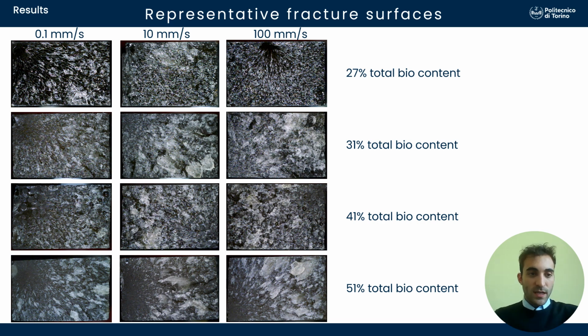Finally, here are represented some fracture surfaces coming from a representative specimen after failure. And as we can see, by increasing the total bio content, so going from the top to the bottom, we can observe slightly more ductile fracture surfaces. Whereas by increasing the strain rate, so going from left to right, we can observe slightly more brittle fracture surfaces.